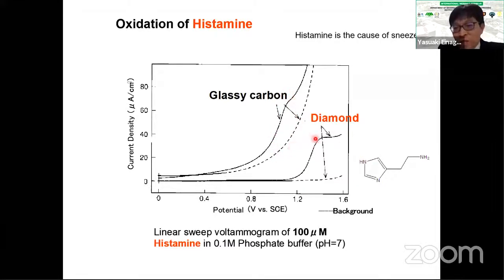On the other hand, when boron-doped diamond is used, as you can see, the oxidation peak of the histamine is shown very clearly, and the background current is very low, so the signal to background is very high, so the sensitivity is very nice. This is a typical example.